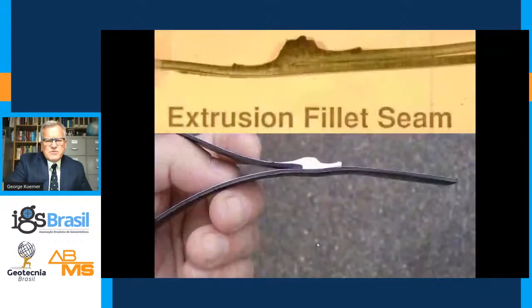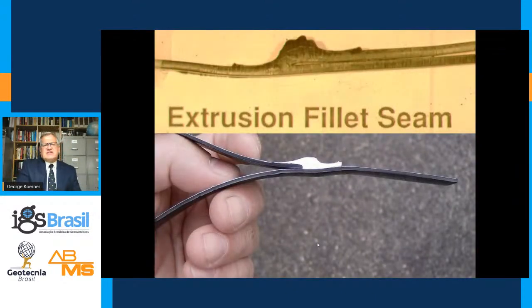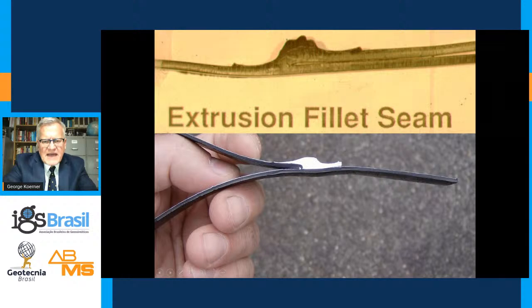The extrusion bead flows over a Teflon shoe and certainly smooth. The location of that bead is extremely important, and you should maximize this distance here for the extrusion bead. In this particular case, it's a white extrusion bead. Maximizing that distance is critically important for a good seam.